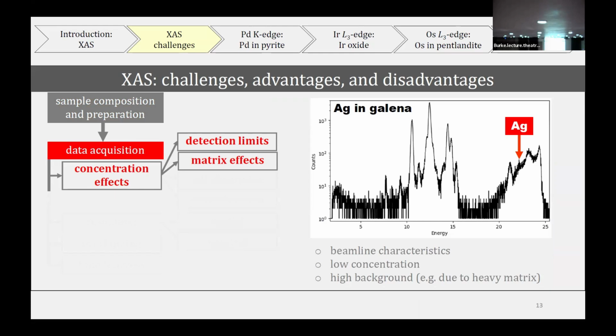The concentrations can be too low. For example, in the case of low concentration, we can hit the detection limit of the beamline, which on most beamlines would be hundreds of ppm. There may be specific dedicated beamlines for very niche compounds which don't give high background. It can be even ppb level, but this should always be negotiated before the experiment. If we hit the detection limit, we won't be able to see anything. And even if we are not hitting the detection limit, we might have some matrix effect.